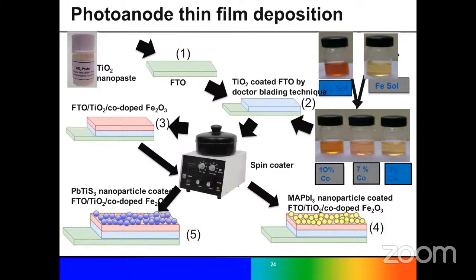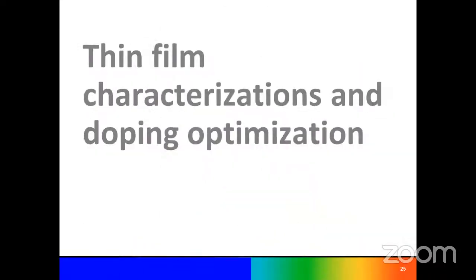by the sol gel process we produce different types of sol with different percentages of cobalt doping, and finally we fabricate these two types of electrodes. These two types of photoelectrode are coated with different types of photoresponse material like MAPbI3 nanomaterial on top. Then finally we check the photoresponse property.